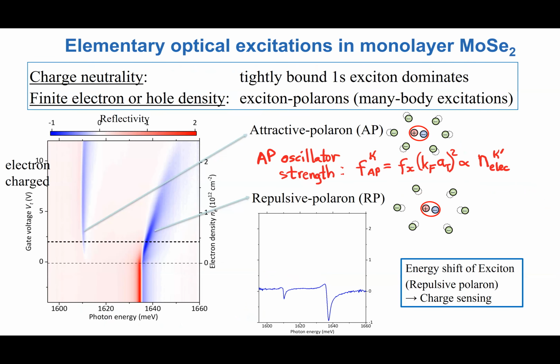So this is the scattering state that is blue shifting, seeing an effective repulsive interaction due to its hybridization with the molecular state, the trion state. And this is the lower branch, which starts out as a molecular state and hybridizes, picks up an oscillator strength. So this is what we describe as an attractive polaron. This is the repulsive polaron. And the reason for that is we can think of these excitations as the exciton distorting the Fermi sea in which it is embedded. In one case, it tries to extract an electron from it. And in the other case, it repels the electrons to form the repulsive polaron.